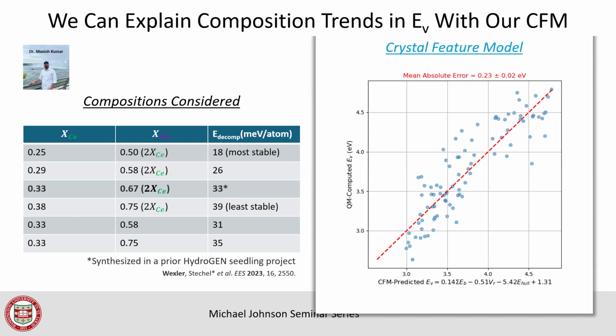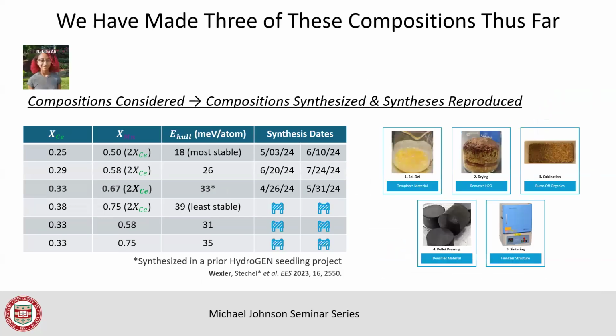So we built that, and it identified that these materials have the energy required to form that oxygen vacancy. It's right in the sweet spot. So what did we do? We went to our experimental colleagues. This is Natalia. She's at ASU, Arizona State, and you see the results, but you don't see that the process is arduous. She went through a lot of different trials and tribulations to be able to make these materials, but ultimately she was able to make a number of these different compositions, with more on the way. What we found is that all of these things are stable. So we can make all of them, all the different compositions that we simulated on the computer.